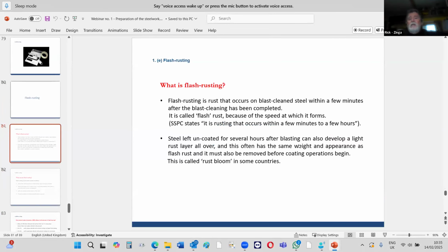Flash rusting is when you blast clean a surface and the humidity is quite high. Normally the critical humidity is about 60%. Also, if you're working near the coast, in a harbor or a coastal region, say within 5, 6, 7 kilometers of the sea, the atmosphere is normally very moist, so it'll flash rust.